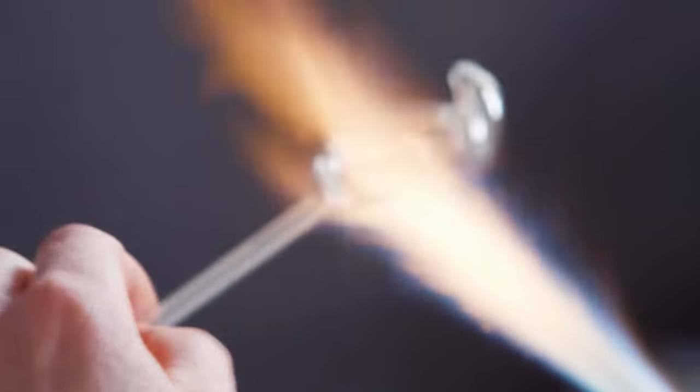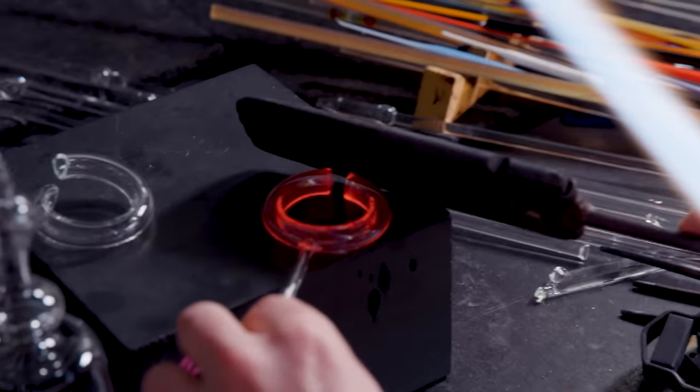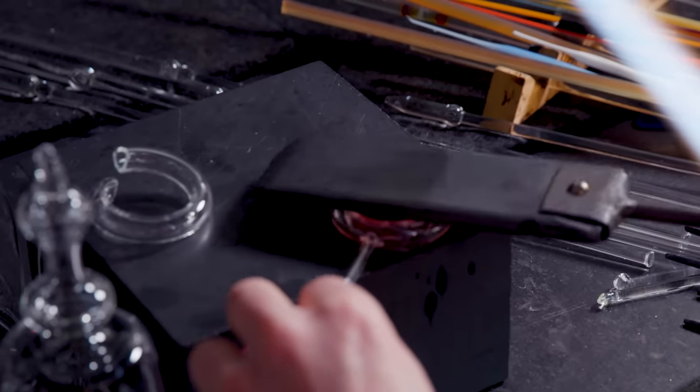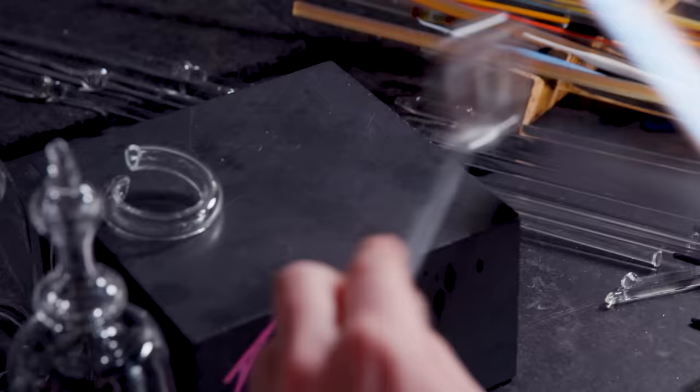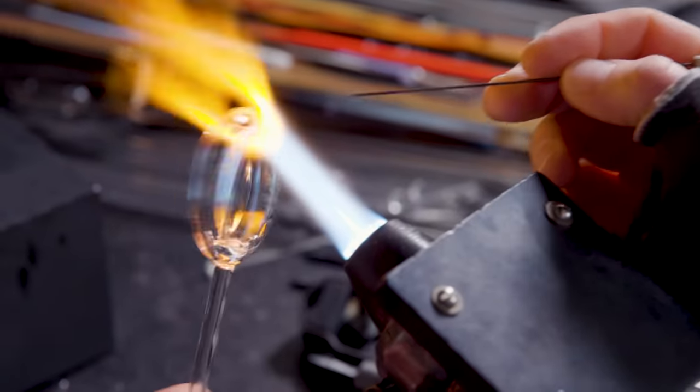And then where I scratch cut it, it has carbide in there. It'll leave a dirty spot in the clear glass, so I peel that little piece off. Then I heat the whole thing, soften it, so I can go on my graphite and flatten it flat. So now I need to pick these edges together carefully, stitch it up.